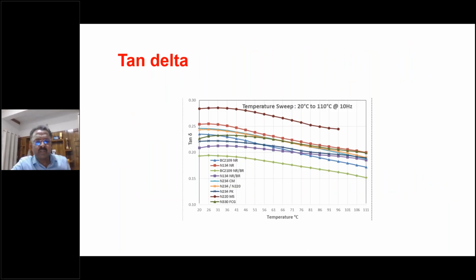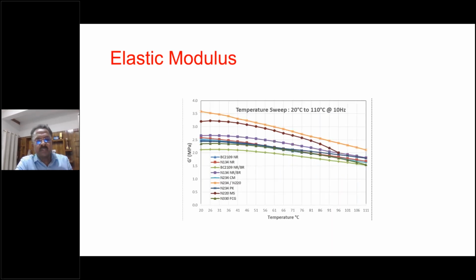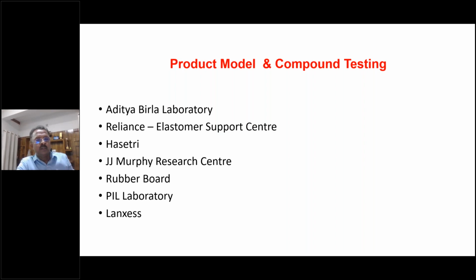So this is the tan delta of different tire compounds. We had nearly 10 tire compounds as test compounds, with tan delta at different temperatures and elastic modulus at different temperatures. So we analyzed the competitors' tire compounds. We almost arrived at their formulations and dynamic mechanical properties. And based on those data, we made certain product models. And these products were tested in major laboratories: Aditya Laboratory, Taloja; Reliance Elastomer Support Center, Vadodara; JJ Murphy Center, Kochi; Rubber Board.